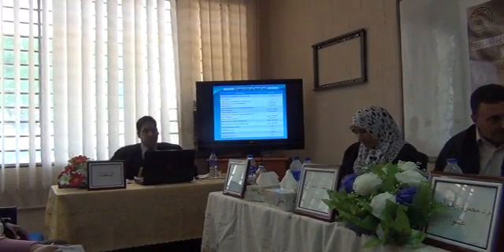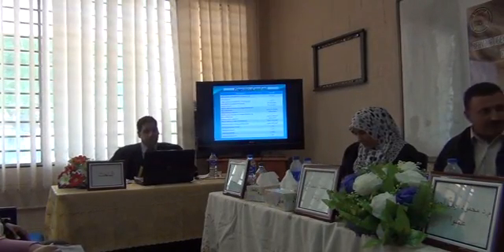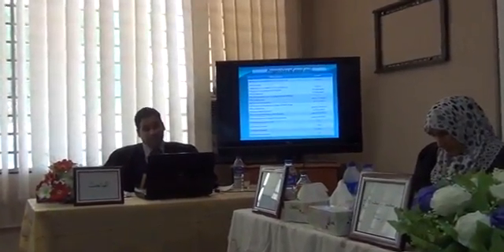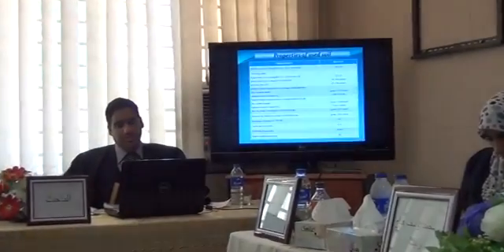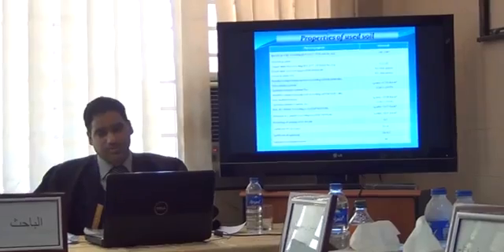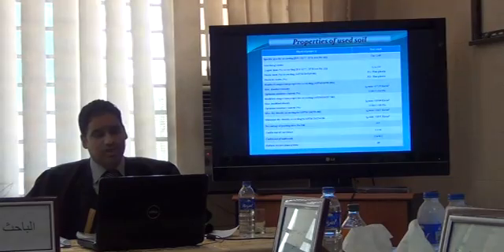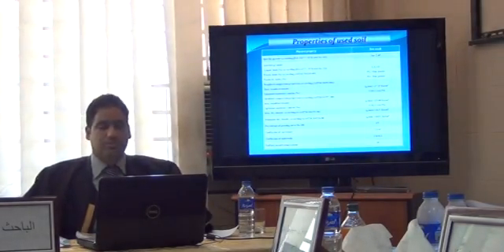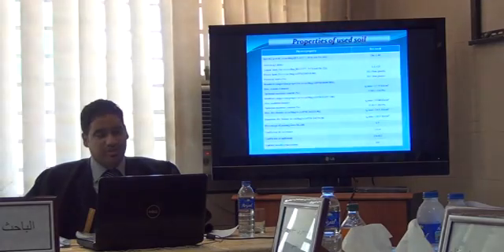This table shows the properties of the gypseous soil. Standard compaction properties according to ASTM: dry unit weight equals 17.25 kN per cubic meter, optimal moisture content equals 14.5%. Modified compaction test: dry unit weight equals 19 kN per cubic meter, optimal moisture content equals 10.5%. Unified classification system equals SP.